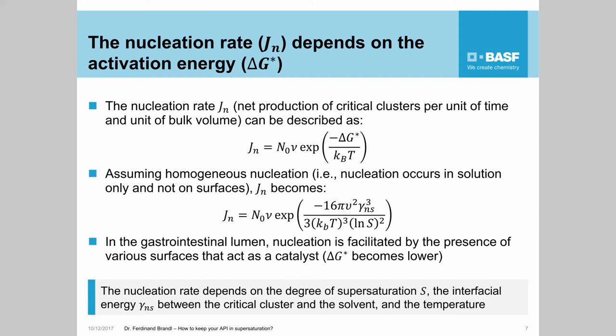The nucleation rate depends on several factors. Looking at the relevant equation, the nucleation rate depends on the degree of supersaturation, the interfacial energy between the critical cluster and the solvent, and the temperature. You should also keep in mind that in the gastrointestinal lumen, nucleation is often facilitated by the presence of surfaces that act as a catalyst and reduce the energy barrier required for nucleation.